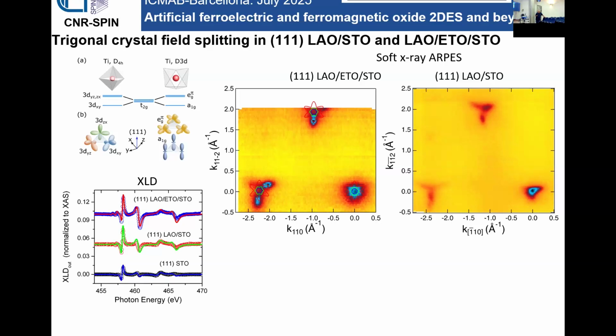For sure, we now have two independent measurements that suggest the trigonal crystal field splitting in 111 LaAlO3 is small. Let's say 10 millielectron volts, I would not like to exaggerate. And typically in this model, they take actually the splitting that I found on the 111. They use the trigonal crystal field splitting we found in LaAlO3. Caviglia also, I don't know why, but they use that one, which in the paper was 20 millielectron volts. Now we know that it's a little bit larger, at least at the gamma point.